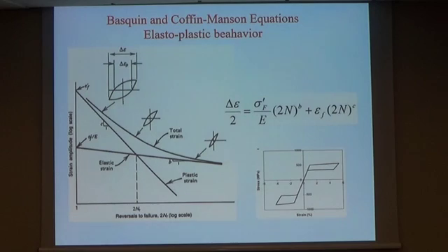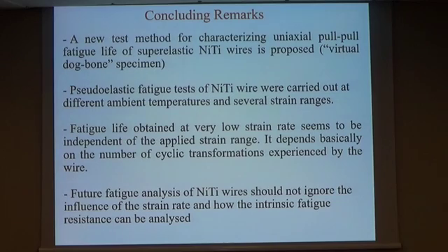We should also remember that in some cases the Basquin and Coffin-Manson equations were proposed to analyze elastoplastic behavior. Here we have some localized deformation and superelastic damage. So we propose a new test method for characterizing the pseudoelastic fatigue life of superelastic wires. We call it a virtual dog bone because we don't change the geometry; we localize the damage there.